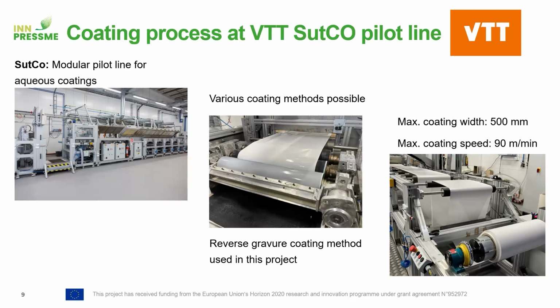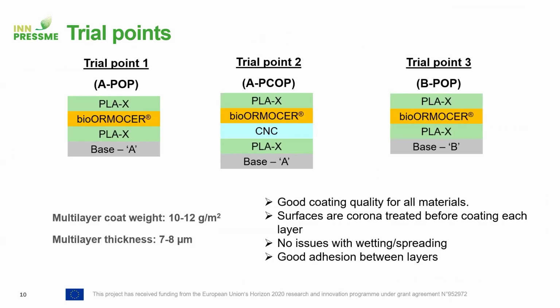Basically, the modularity means that you can modify where each of these compartments is located to serve the customers, so you can tune the structure of the pilot line. In addition, there are various coating methods possible on SutCo, and in this project we used the reverse gravure coating method. So the trial points are here. We have three different trial points that we tested.